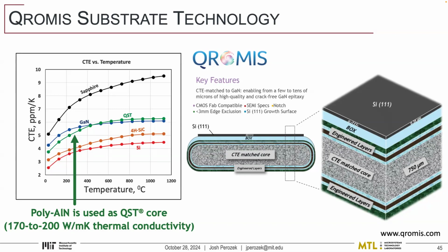It turns out that thickness is between like 5 and 7 microns. Past that, it's very challenging to make, but we need double that. We need about 15 microns of GaN. So we've been able to partner with this company, Qromis. They've been providing substrates for this work. They have a very nice engineered substrate that is thermally matched to gallium nitride. So you can grow arbitrary thick layers and they cool down at the same rate so that nothing cracks.